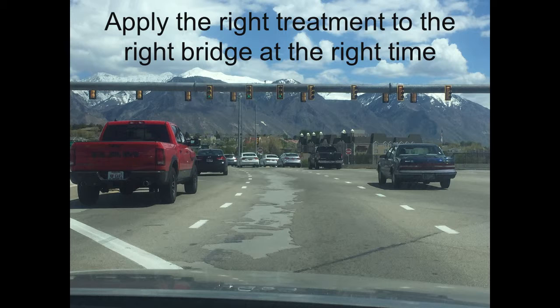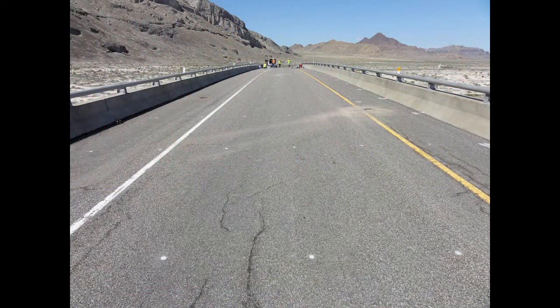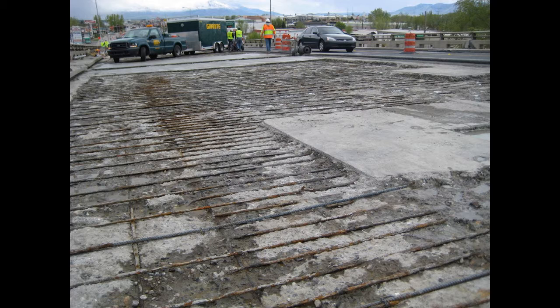I've shown a picture of a bridge deck with an overlay that is partially debonded — does this need a treatment? Yes. Would it be as simple as repairing the overlay? Well, it depends: how long has the bridge deck been like this, how many winters have occurred, how much salt has penetrated that opening in the surface treatment, are there delaminations lurking beneath the surface? Some of these are difficult to determine without something more than visual inspection. For another bridge with a bituminous overlay — I see cracking in the bituminous overlay, there's also a membrane beneath that asphalt; is it leaking? Would it be 10% delaminated or instead 10% intact? Knowing in advance the condition of a bridge deck can help us determine the appropriate treatment to apply.